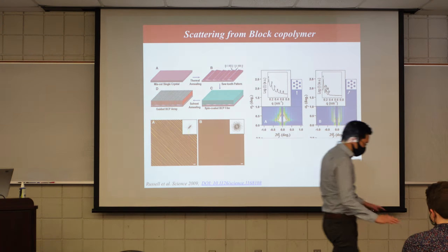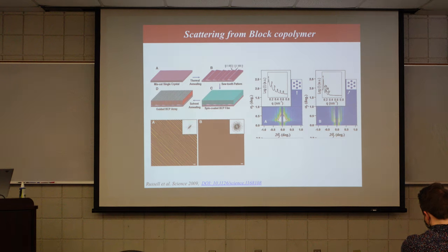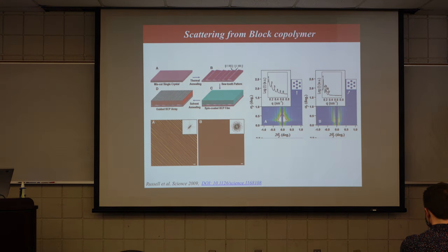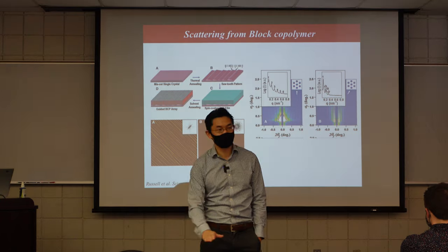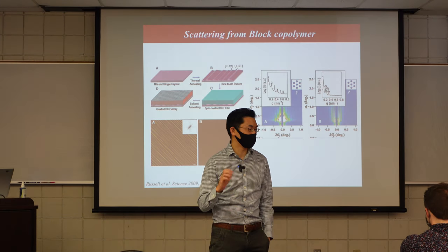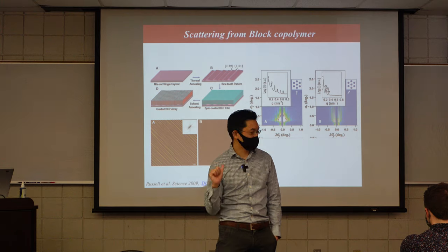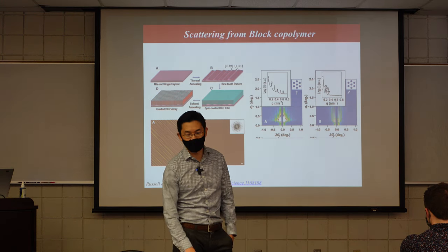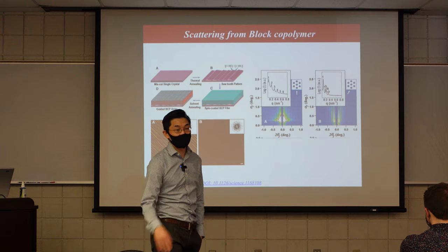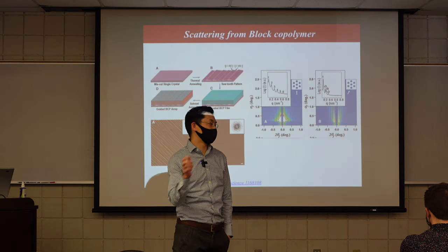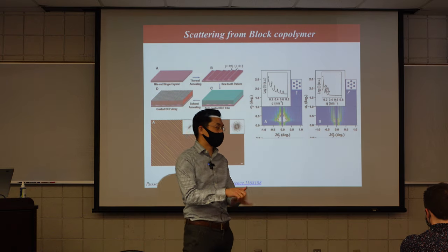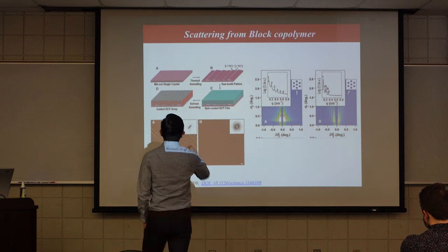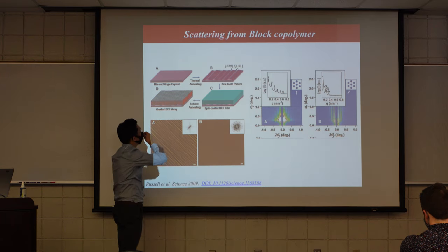You can think about there's a giant magnet on the floor. Then it's going to stick me. I'm going to lie down horizontally. He did a great job to control the surface energy. So he thought about how can we neutralize the surface energy. Then you can make the block polymer stand up. So one way, back in 2000, Tom did was to make a neutral surface. So your surface is not favorable for block A or for block B, then once you're in the incommensurate thickness range, your block polymer will stand up. So that's some of the reason you can see these block polymers standing up.